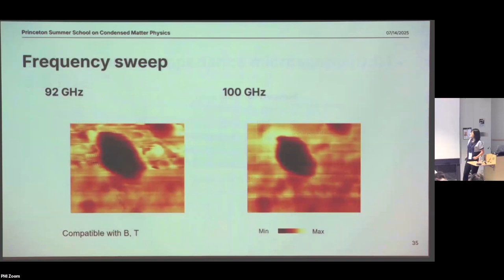But more than that, because of this photonic cavity design, we can now do frequency sweeps. So there's 92 gigahertz and there's 100 gigahertz. They look kind of similar, because there aren't specific modes of graphene inside this regime, but we can now do the whole W band from 75 gigahertz to 115 gigahertz. So that's just the first step of reading out all those different modes and fragile states in this frequency regime. And also because we're using a dielectric type of cavity, it's finally compatible with magnetic fields, and it can be done at all temperatures without being limited to below Tc for this type of sensing.